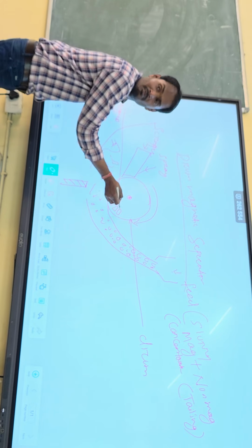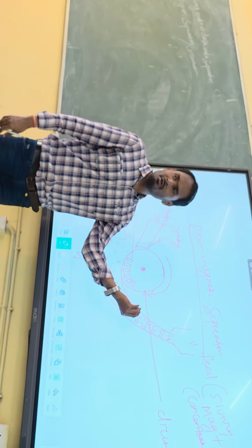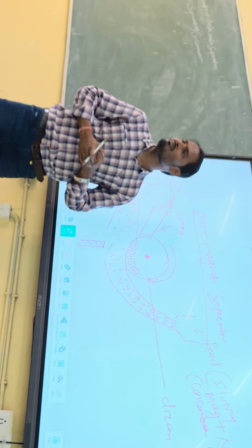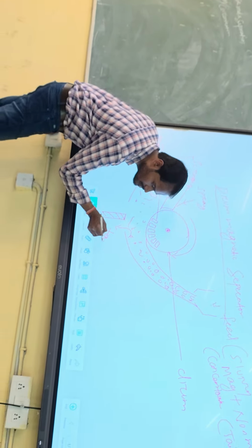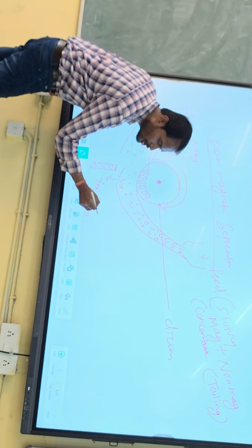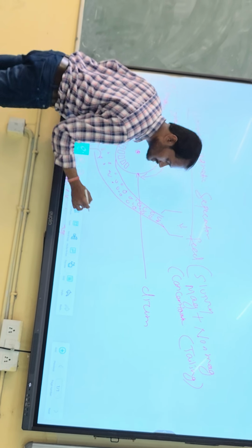And here you have magnets. This entire drum is not made up of magnet, only the bottom part is made up of magnet, right? And it is rotating. So what will happen? The minerals which are magnetic in nature will just stick to the drum, of course. Yes or no? But the minerals which are not attracted to the magnet will simply fall down. So most of the minerals which are non-magnetic will fall down. So this will be your tailings, or I can say non-magnetic. Is it okay?